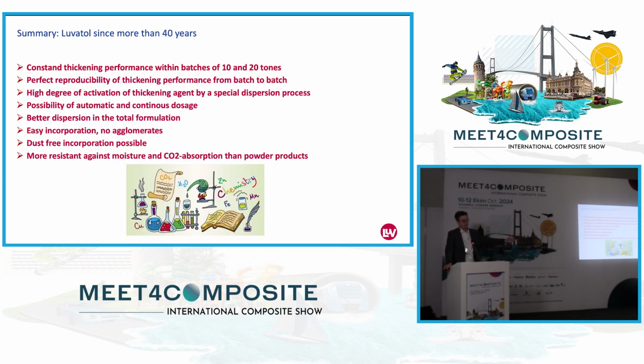So to summarize, since we have produced this for quite a long time, you get a constant thickening performance, a perfect reproducibility, you have a high degree of activation, and you can rely on our help if there is something off, if you have a new product, if you need a new Luvatol type. It's easier to disperse. You have no agglomerates, which you normally have to filter out at the end.